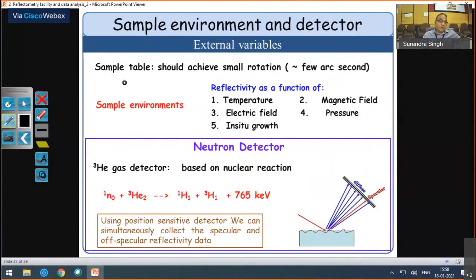Then the sample table. Yes, the sample table, because as I said, we have reflectivity over there, and that very quickly falls down. So we have reflectivity within 1 degree or 2 degrees angle of incidence. So we should have a robust sample table, which should be able to take all the sample environment things like temperature stages, electric field stages, or if you want in situ growth over there. All those arrangements should be available on your sample table: magnetic field, pressure. All these things can be done on the sample table.